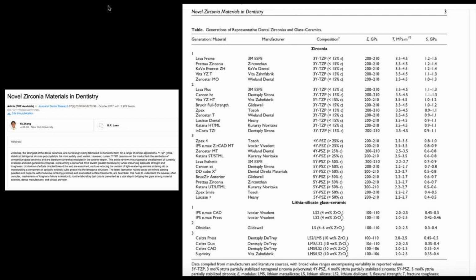And then you have the Zpex from Tosoh, you can see that. Those are 4Y zirconia, and then you see the Zpex Smile at the bottom, which is the 5Y. And of course, you can see all the strengths and everything else, from literally glass ceramic crowns, etc. Once you get to the 5Y zirconia, you can have some that measure 600 megapascals to 800. They don't go much higher than that. So don't fall for a million megapascals.